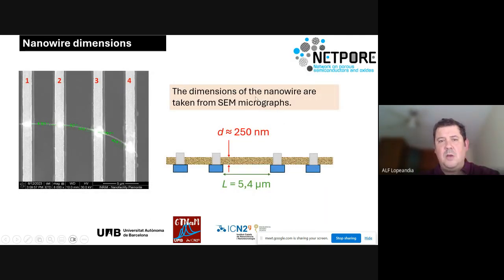If we want to obtain the thermal conductivity, of course, we need the dimensions of the nanowire. Here we have the diameter, around 250 nanometers, and the length. We can determine the length with quite good precision, but for the diameter the uncertainty is the dominant one in the final measurement, because determining the real diameter of the nanowire, considering the contrast and everything, is quite difficult. We can consider that we have around 10% uncertainty in that measurement. That is not that much.